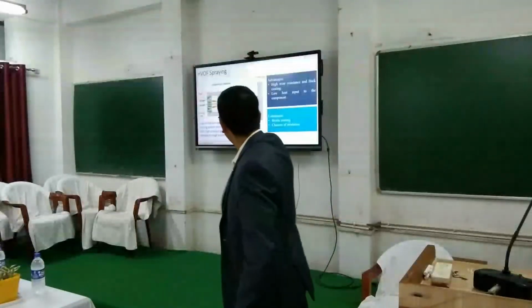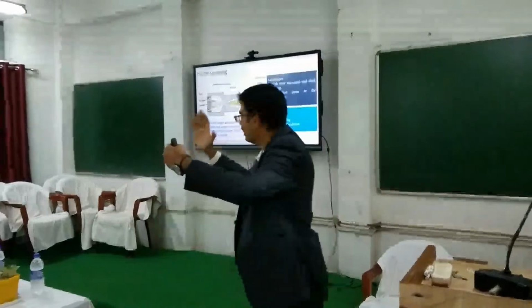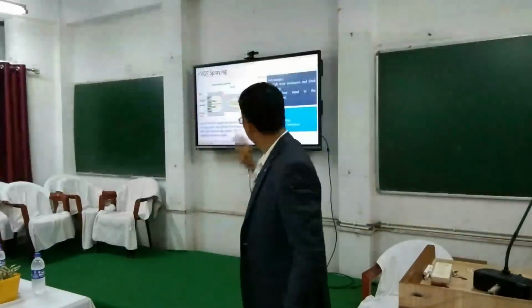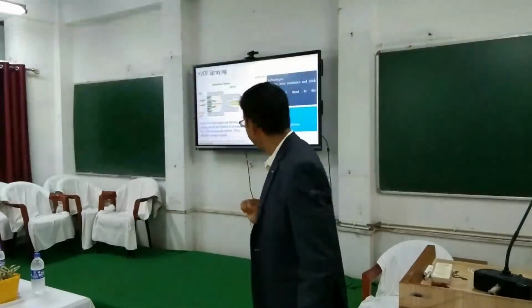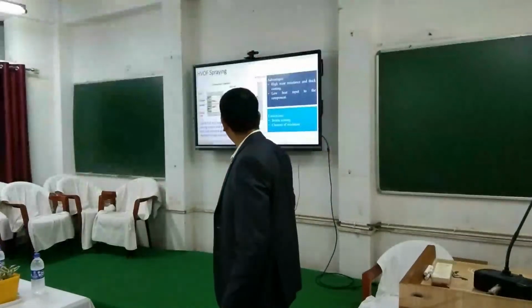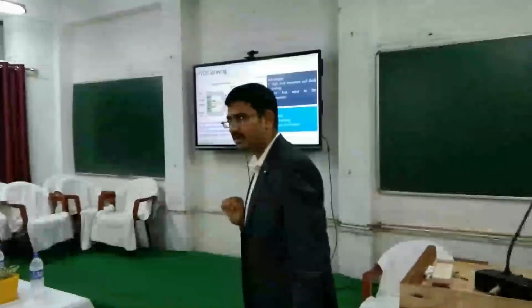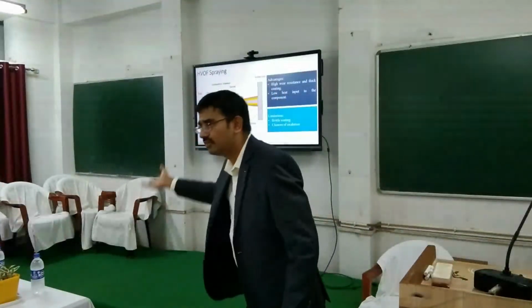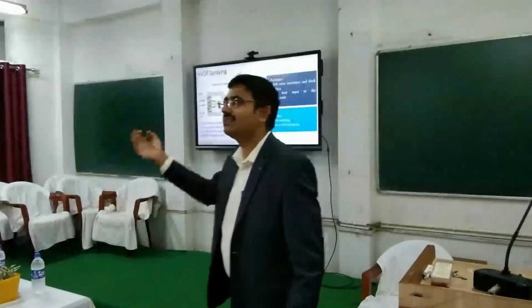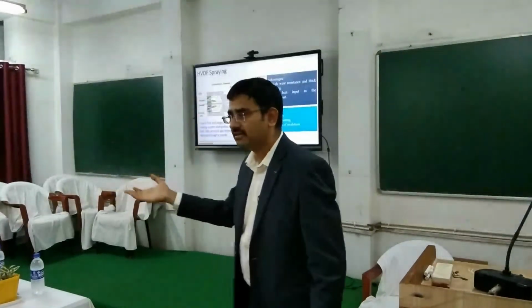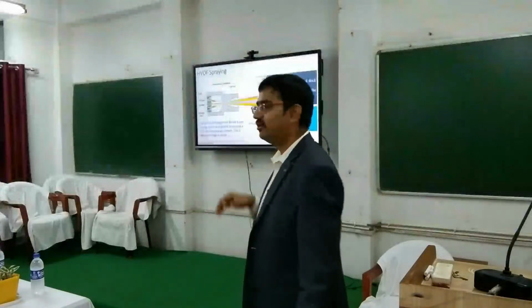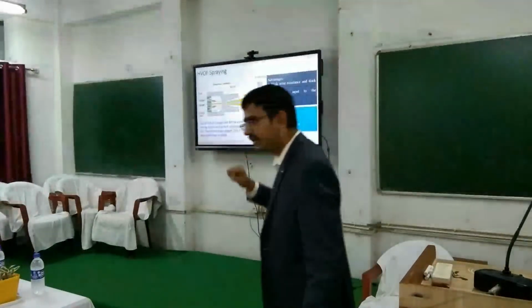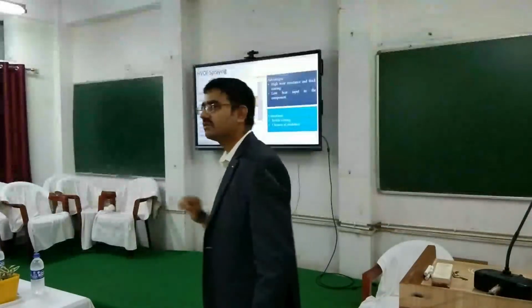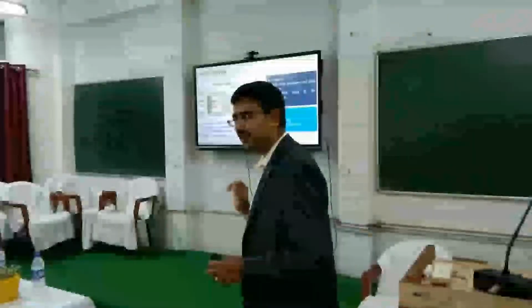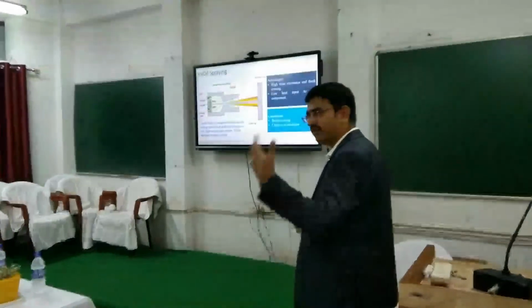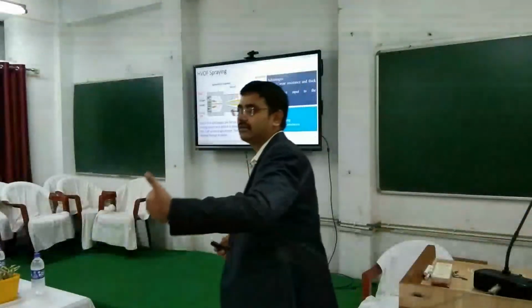to the component. You can change the distance between the gun and the substrate, so that there is minimal heat transfer to the substrate. Limitations: brittle coating and chances of oxidation are more, because you are sending an oxy-fuel mixture. If your material is very sensitive to oxygen, if it will oxidize like aluminum, then alumina formation will occur. If that is not desired, then this process is not very suitable. That is one limitation of this process. But the advantage is you can coat metal matrix composites directly.